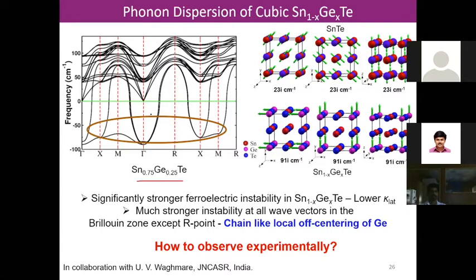That means if you do the Fourier transform, we can understand there is a local off-centering of germanium in the lattice, coming from the 4s2 lone pair of the germanium, because the 4s2 lone pair of germanium is much more active than the tin lone pair. So that forms a local off-centering region in a global cubic structure.